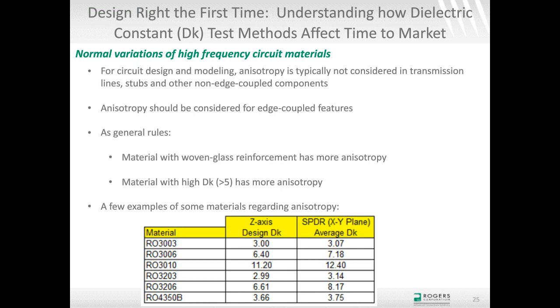As you go up in dielectric constant, with the RO3006 laminate, you can see there is a bigger difference, and with the RO3010 laminate, you can see a very significant difference. And also, if you want to look at the difference in glass, the RO3003 and the RO3203 are the same materials, except the 3203 has glass reinforcement, and the RO3003 doesn't. And you can see that the RO3203 has a little more anisotropy than the RO3003. So these are kind of general trends to keep in mind.